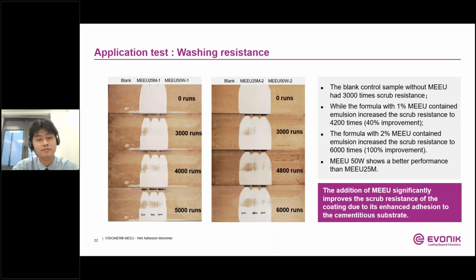The blank control samples have 3,000 times, while the formulation with 1% MEU-containing emulsion increased the scrub resistance to 4,200 times. It means 40% improvement. And the formulation with 2% increased the scrub resistance even to 6,000 times, which means 100% improvement. MEU50W shows a better performance than MEU25M in this case. Therefore, the addition of MEU significantly improves the scrub resistance of the coating through its enhanced adhesion to the cement substrate, which is one of the most important mechanical properties for the construction paints.